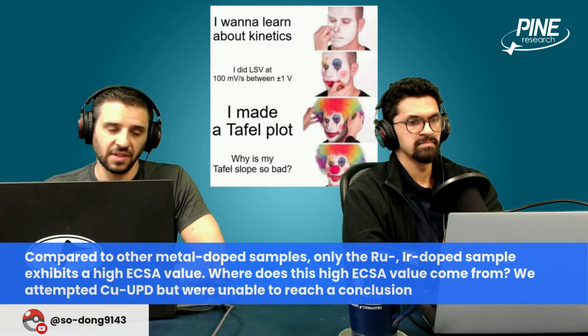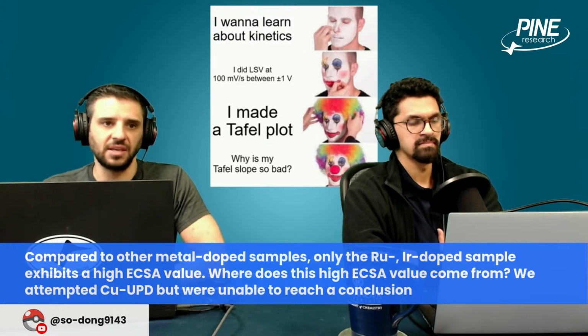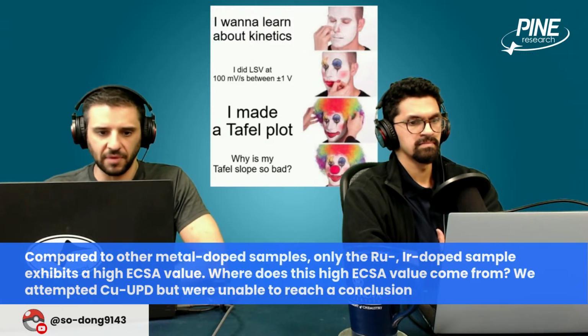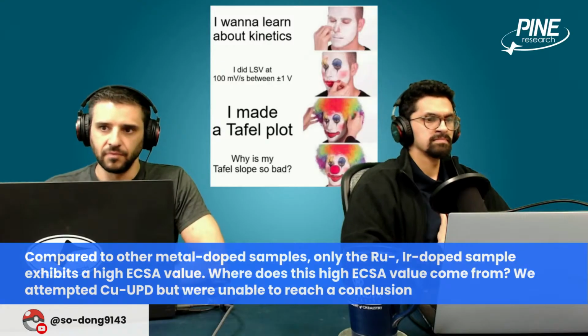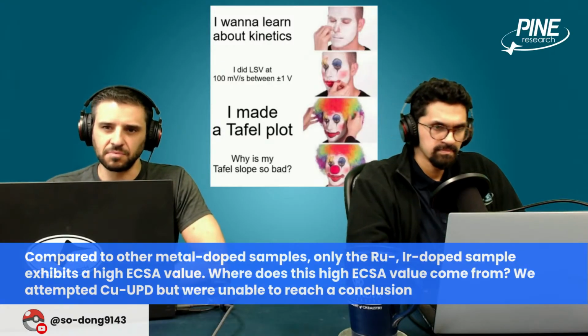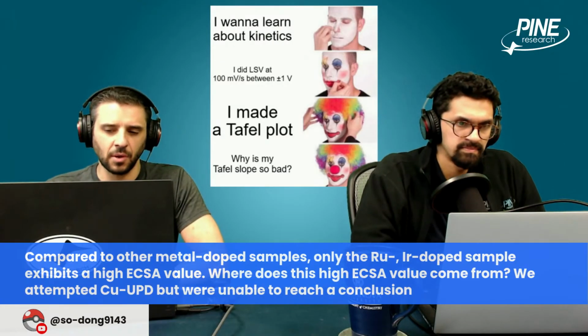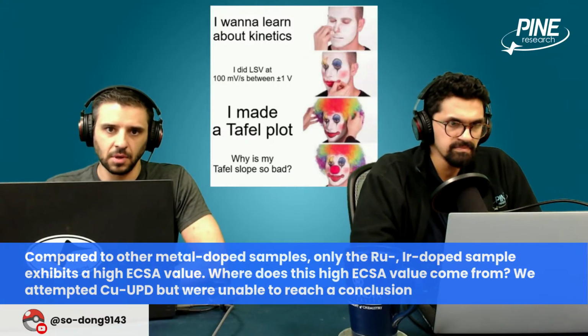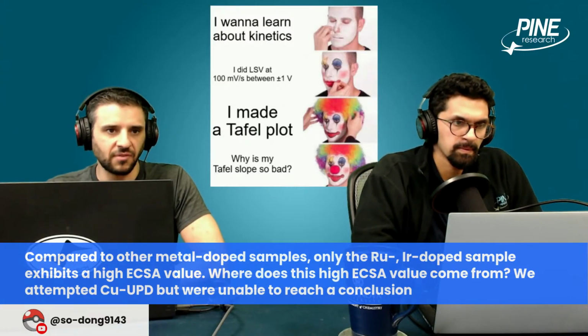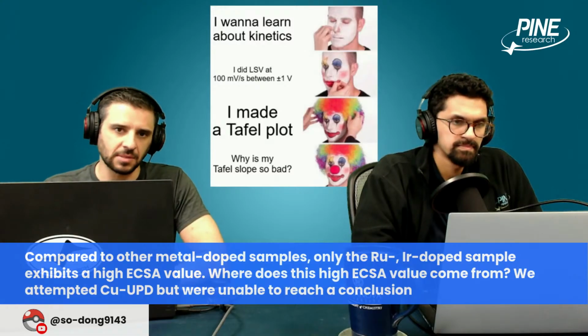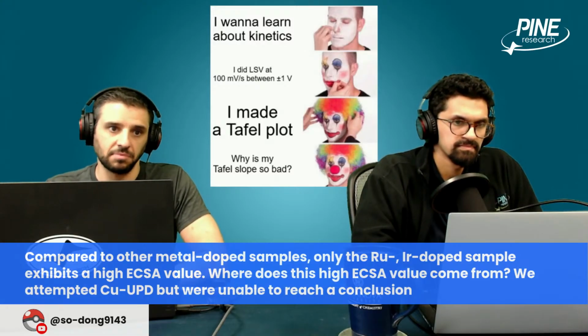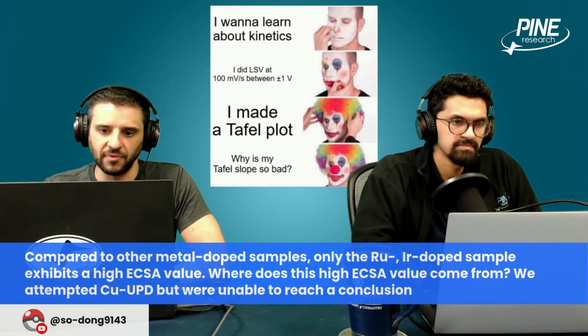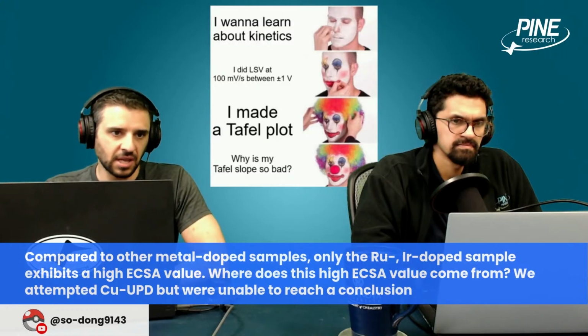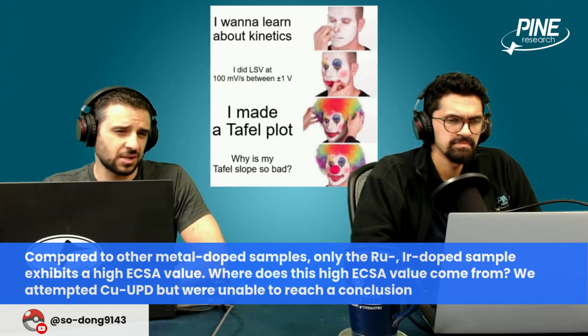The other could be, let's say in a perfect world, you have exactly 5% doping on all, they're all perfectly the same doped. What you've said isn't particularly surprising, although I'd have to see compared to what. If you're comparing it with platinum and palladium, that might be surprising because platinum and palladium are generally also high performing catalysts. But if ruthenium and iridium are performing better than nickel and manganese or something, I wouldn't necessarily be surprised.